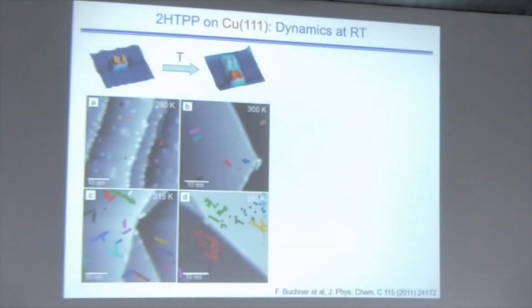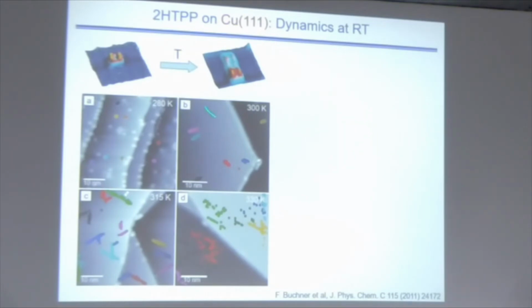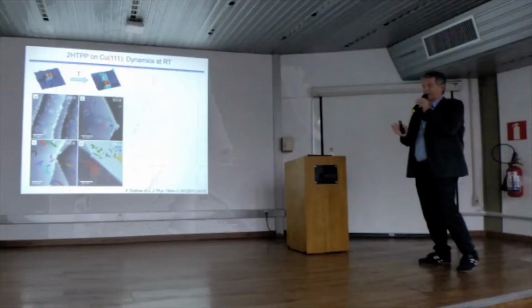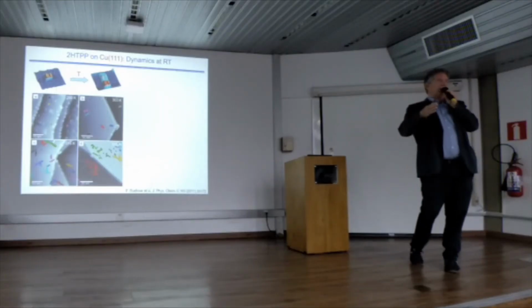So we did images at different temperatures. Here you see low temperature. We color-coded individual molecules, and then we superimposed again these 20 images, and here you see nothing happens. So all molecules stayed at the same spot, all are sharp. And then you increase the temperature, and you see they move in one certain direction or in this direction. And you increase the temperature further, then you see this direction, vertical, and this direction. And then if you go too high, it's getting a little chaotic, although the same behavior is still there. And what you see here and here, sometimes they change their direction. Sometimes, obviously, the energy is high enough to rotate by 60 degrees, there's an equivalent direction,